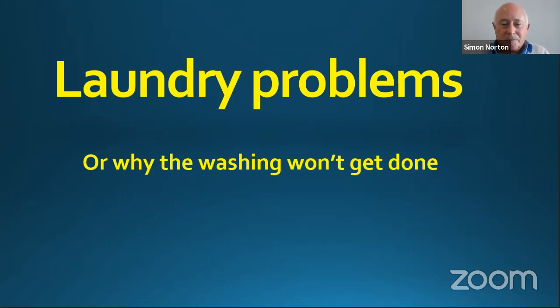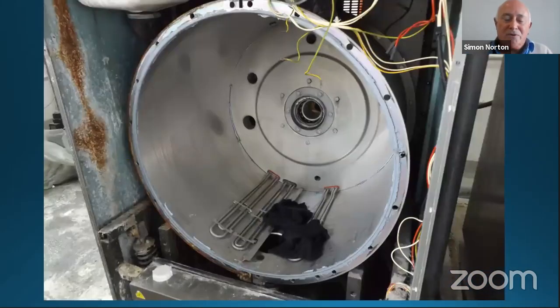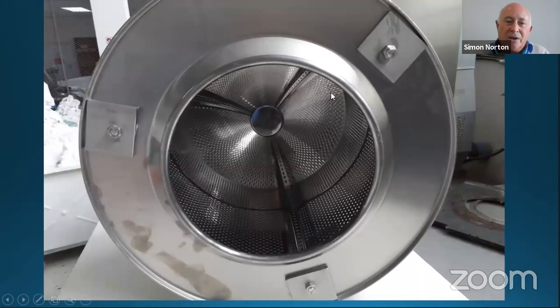So this is part of the industrial washing machine that failed. The interior consists of stainless steel. We didn't check that because that's not where the failure occurred. Just out of interest, this material here is what we call pre-galv, or continuous galvanized sheet, with a very thin zinc coating. This material here is probably a ferritic stainless steel in the center. This is the actual drum in which the washing took place, but that was not the issue.